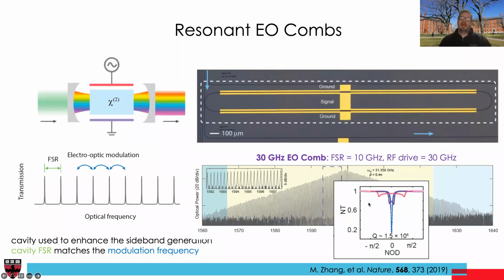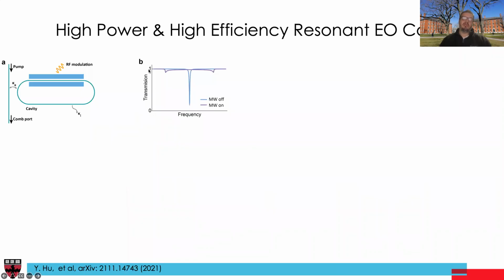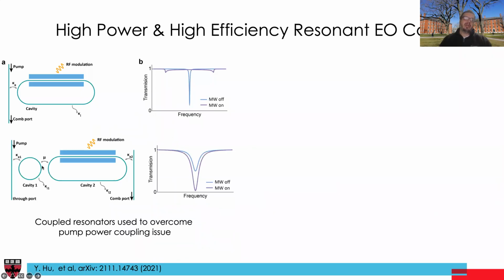And so that was a problem that prevented us from making this really broad comb. And a student of mine came up with a very elegant solution to this problem. Without going into a lot of details, he realized that the trick is to make sure that the resonator is critically coupled at the pump frequency when RF is on. He was able to achieve this by introducing an additional ring resonator, forming what we refer to, as well as the community broadly, as a photonic molecule, and more about this I'll tell you in a few slides. So with these coupled ring resonators, by carefully controlling coupling rates in different loss channels, you can get maximum power transfer from the pump into this comb ring when RF is on.